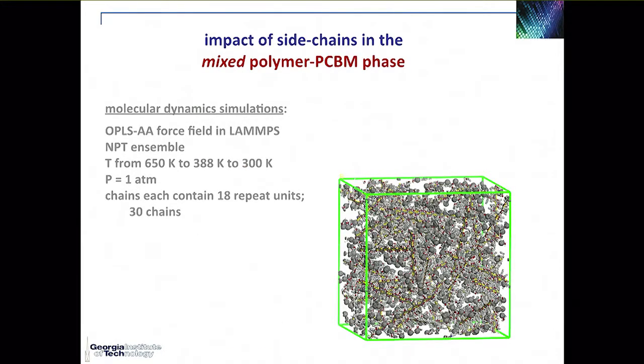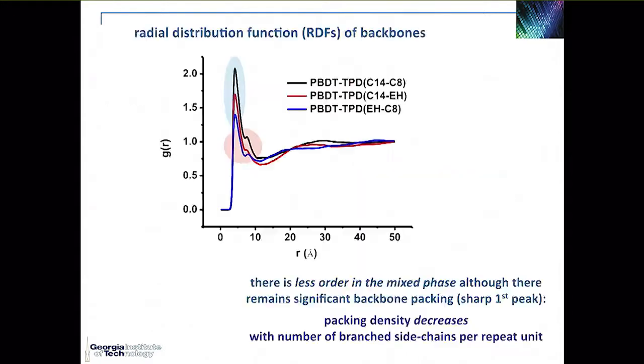Then we went to look at the polymer fullerene mixed phases. And again, did extensive molecular dynamics simulations, taking advantage of the supercomputer at KAUST. And in that case, the message from what we learned from those calculations is that there is, of course, less order in the mixed phase than what we had in the pure phase, which is what you would expect because of the mixing. But also importantly, the packing density decreases with the number of branch side chains per repeat unit, which is not surprising either. But what it tells you is that if the packing density decreases as a function of those larger numbers of branch side chains, that means that it will be easier for fullerenes to come and interact with the polymer backbones.